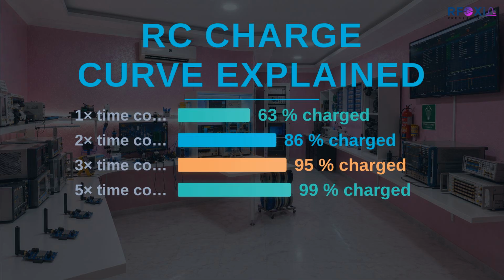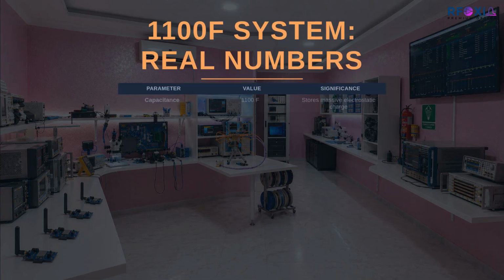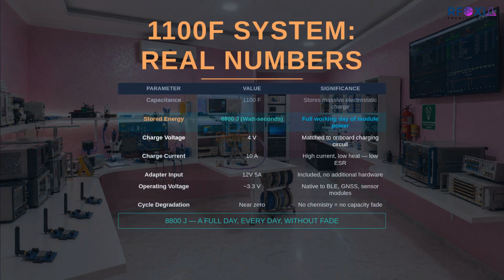The 1100 farad supercapacitor in the Multinav Pro Plus Power program kit charges at 4 volts, accepting 10 amps from the included 12 volt 5 amp adapter through the onboard charging circuit. Let me put the stored energy in numbers because people underestimate what 8,800 joules represents in practice. A joule is a watt second. 8,800 joules delivered at the roughly 3.3 volt operating voltage of the modules represents enough energy to sustain continuous operation at low to moderate current draw for well over a working day in normal field deployment.